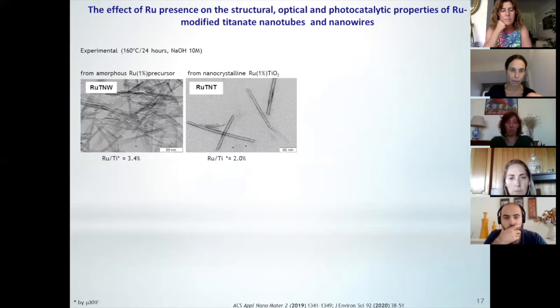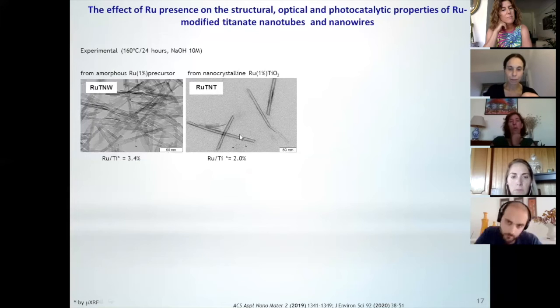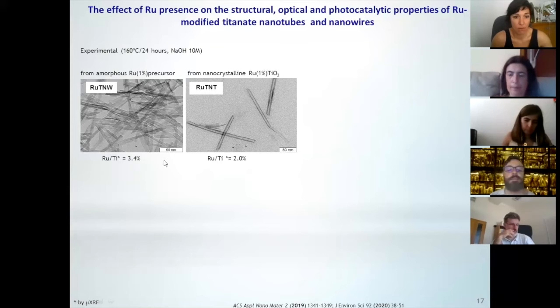We know that we must prepare a precursor, a doped precursor. We have 1% nominal precursor with ruthenium, and I think you already know that we can prepare titanate nanowires directly from the precursor. If we prepare first TiO2, then we will be able to prepare the nanotubes. If we look at the amount of ruthenium, remember we are starting from the same precursor, we see that we have a lower value when we are talking about nanotubes.